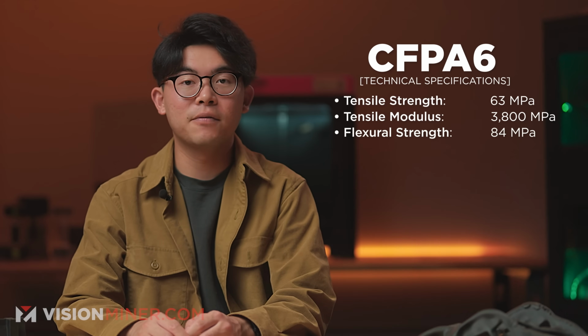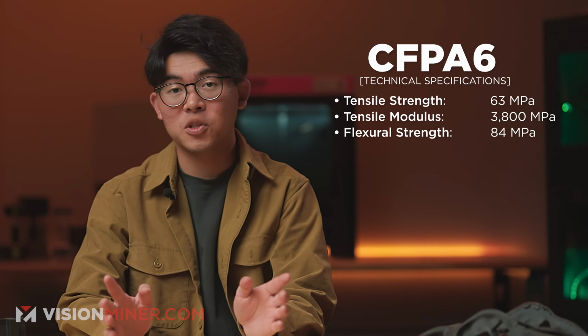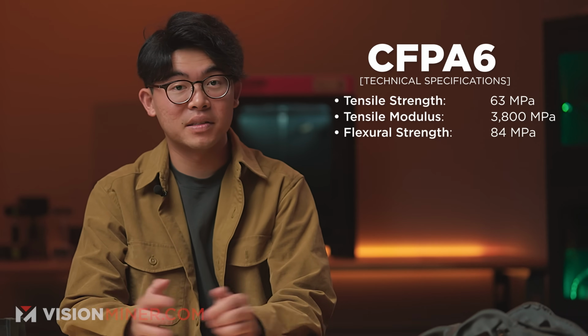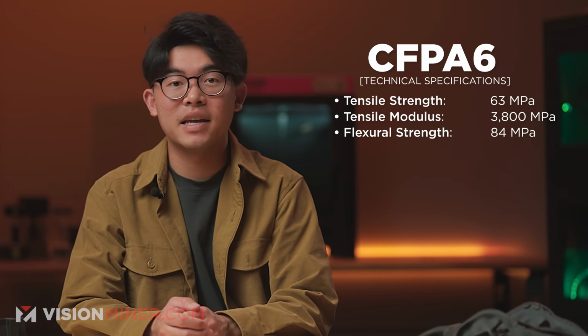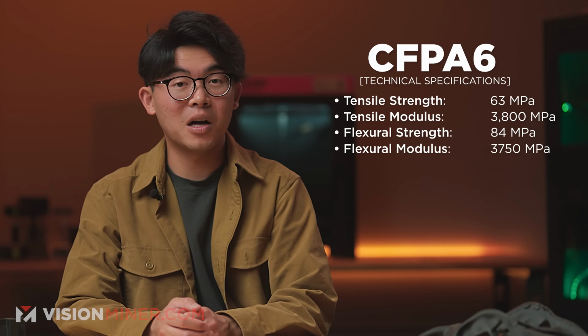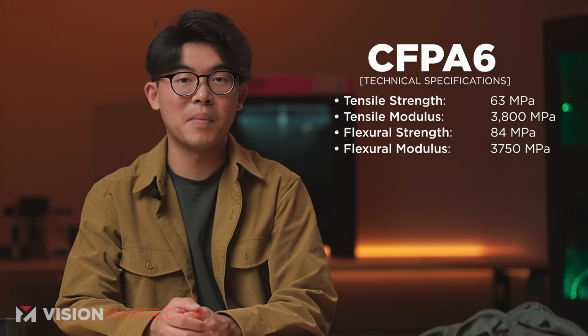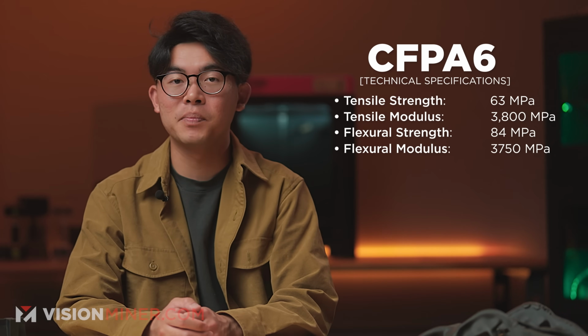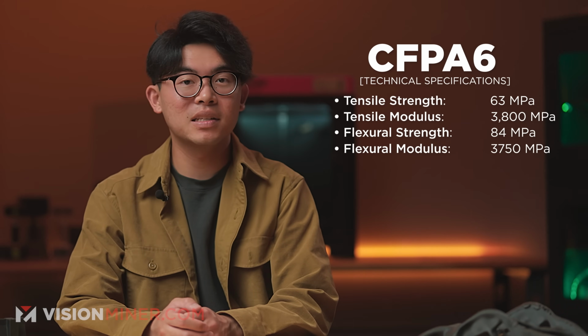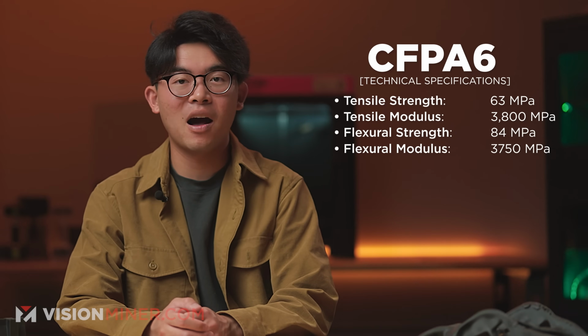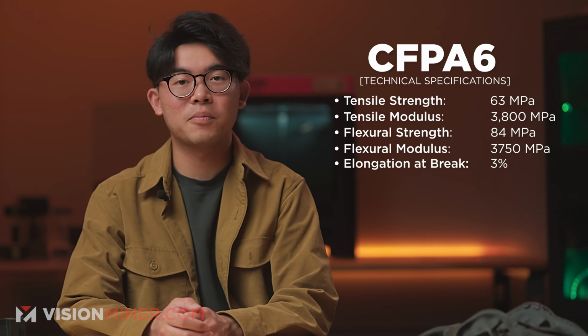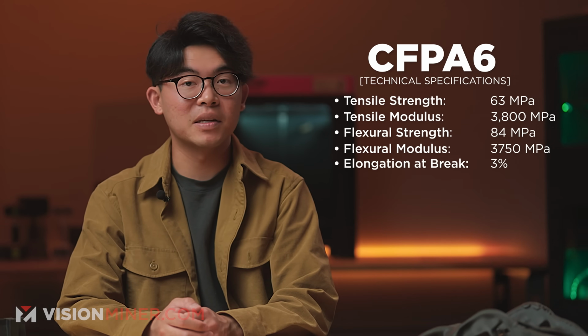Flexural strength, 84 megapascals. This indicates how much stress a part can withstand while being bent. It's crucial for cantilever brackets and load-bearing structures. Flexural Modulus, 3,750 megapascals. This tells you how resistant the material is to bending. Parts that need to maintain shape under pressure benefit from a high flexural modulus. Elongation at break, 3%. This measures ductility. Lower values like this indicate a stiff but more brittle part that won't stretch much before breaking.